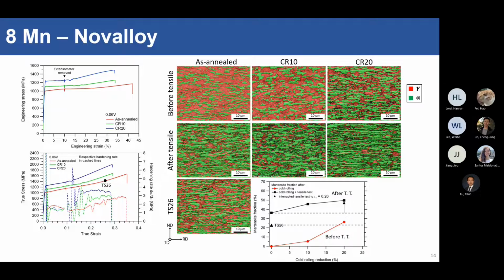And we did an interrupted tensile test here at TS26. So from the as-annealed, we pulled it to about 0.26 true strain. This TS26 sample was meant to have the same equivalent strain as the cold roll 20 sample here. But as you can see from here, somehow when you continue the tensile test, you only get this much martensite. Whereas for your cold roll 20, you have the same amount of martensite here, but you get way more martensite after the end of the tensile test. So we wanted to know why, what's going on.